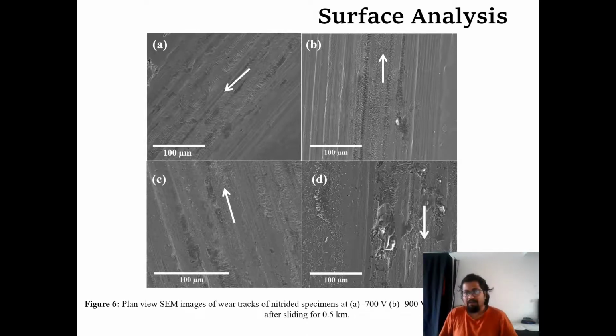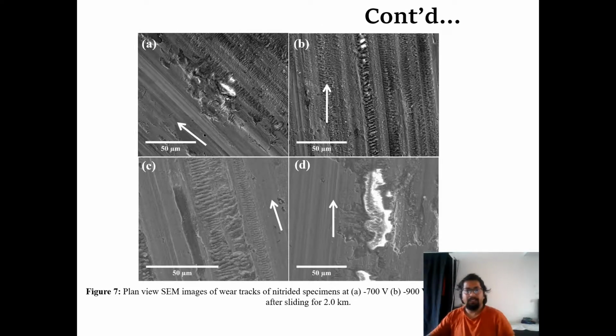In 700 and 900 volt, mostly there were grooves, and these grooves were filled with debris. Whereas in the case of 1000 and 1100 volt, in some places a lot of chunks of the layer were removed. We can say plowing behavior was there, and at higher magnification we can see the same thing which I said for the low magnification. Here we can see that the grooves are wider and deeper with the increase in bias voltage, as well as sections of the nitrided layers being removed in many places.